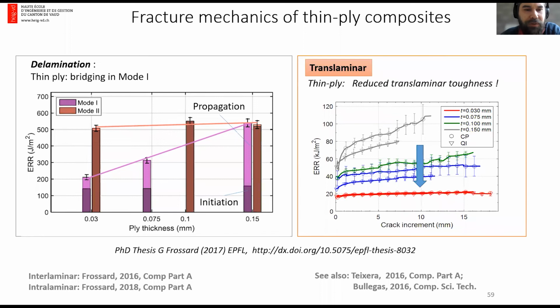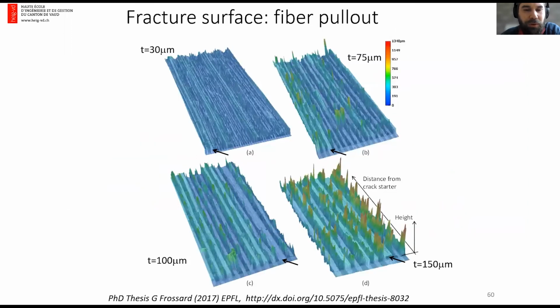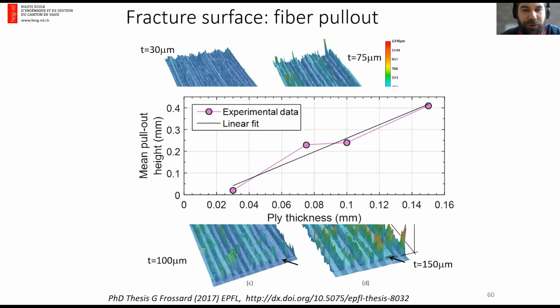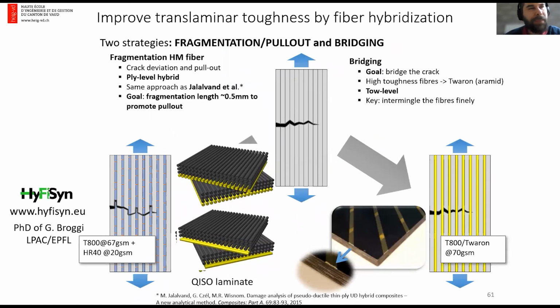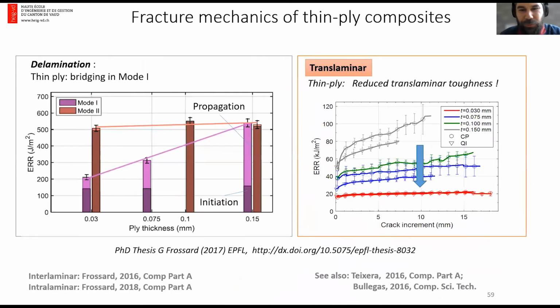However, this brittleness can be linked to the pull-out length during the fracture, and this pull-out length can actually be restored using hybrid fibers. So that's the subject that we are working on now with the PhD of Guillaume Brogy in the HyFiSyn European project, where we use two types of fibers, one with a lower strain to fracture and another with a higher strain to fracture, in order to promote pull-out. And with this, we can restore at least partially the disadvantage that we have with Thin-Ply. It's still work in progress, but that's one way.